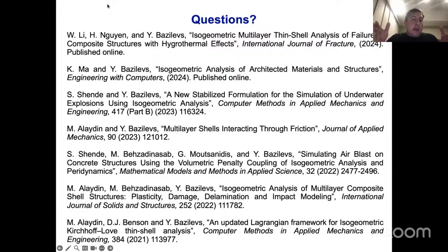So you can do the math, and you end up with about 100 by 100 or 200 by 200 discretization on each individual ply. And then you would want to do 16 plies or 24 plies. You can see that the degrees of freedom explode completely. And then, trying to do this at the structural level is out of reach.